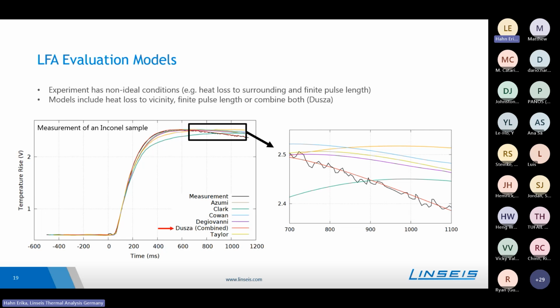So there are a lot of scientists who thought of how to correct these effects, and there are a lot of different models. But mainly the well-known models either consider the heat loss or consider the finite pulse length. What is unique for our instrument is that we have this model developed by Dr. László Dusza, which is the so-called combined model. This model considers at the same time the heat loss as well as the finite pulse effects, so that this evaluation model is quite universal and can be used for almost every material, so that it's our default model for evaluating almost every sample we test.